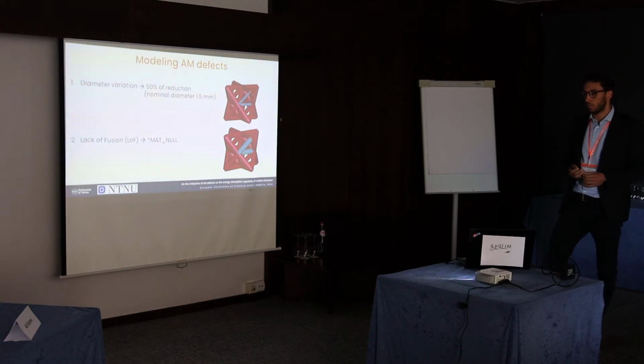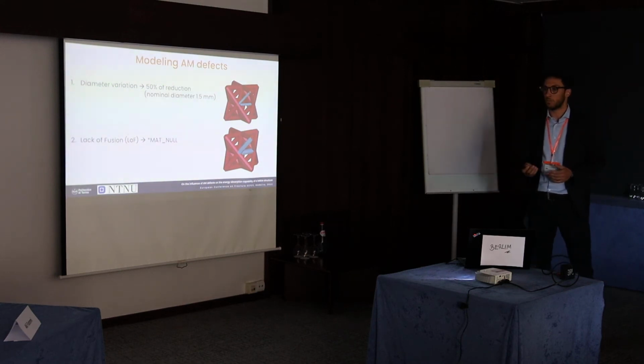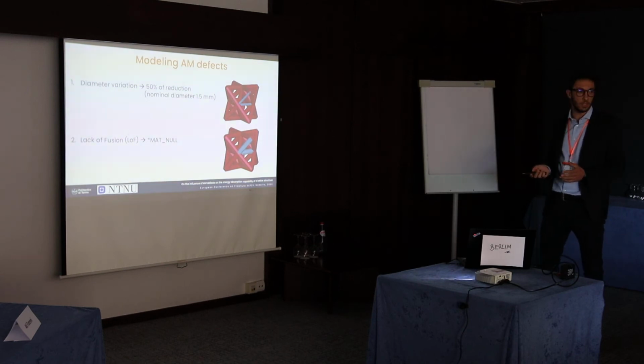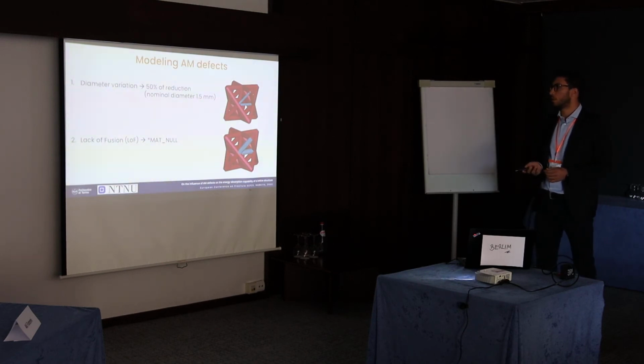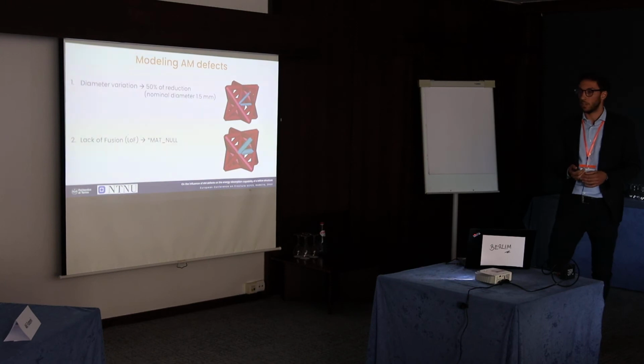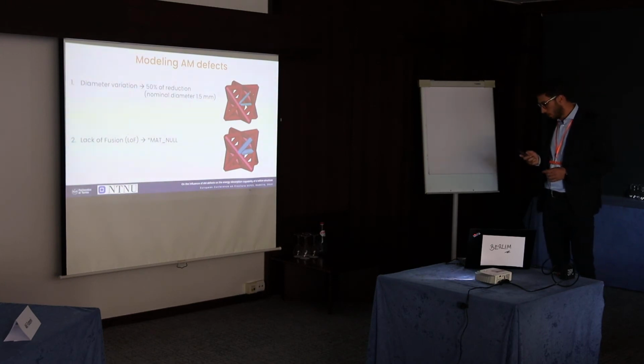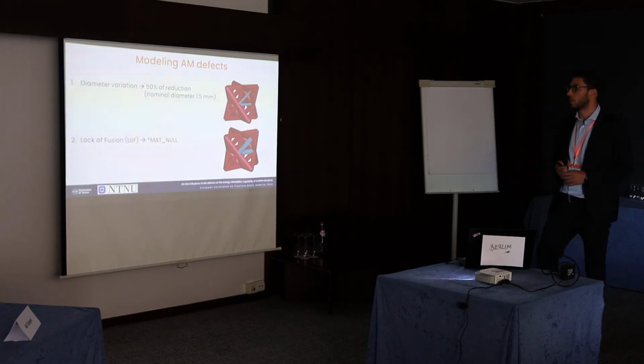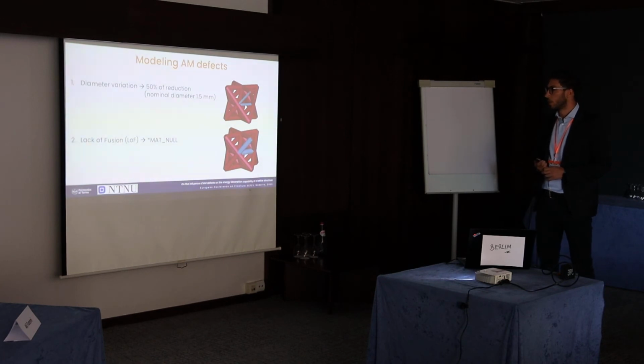This was mainly due to the fact that during some optical observations that we made on the specimen that we produced, we were able to see that there were consistent variations of the diameter from the nominal value that we selected. And the second defect that we considered is the lack of fusion.